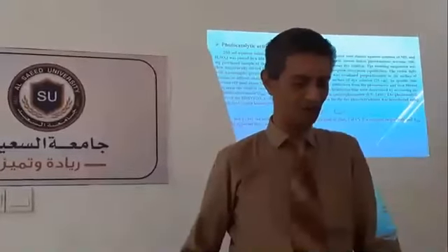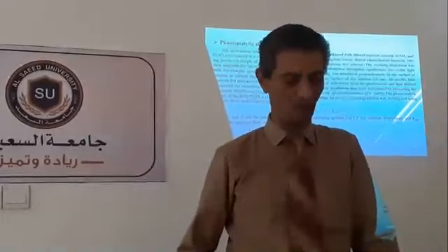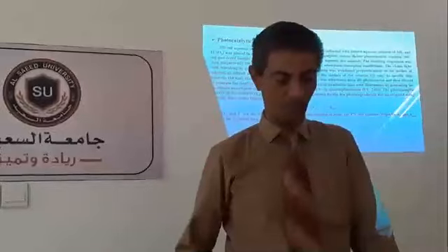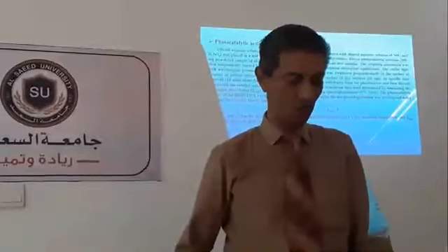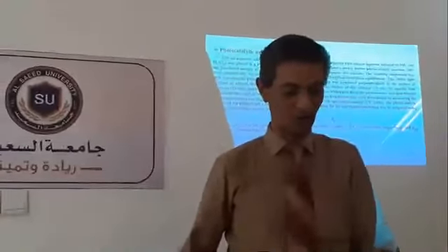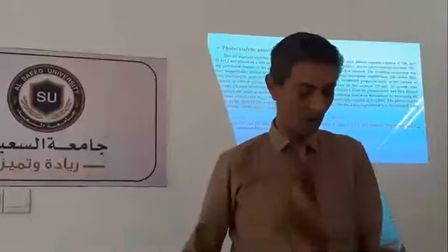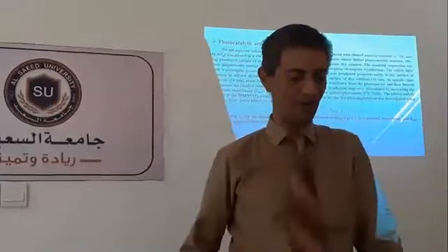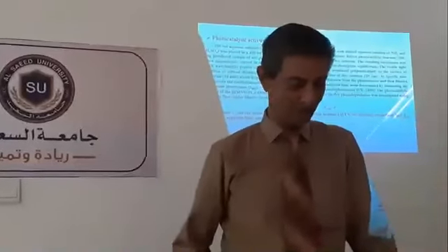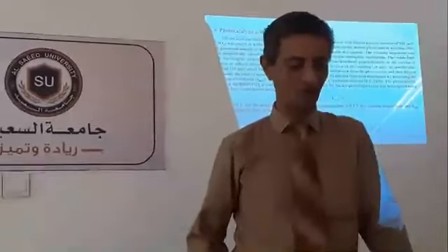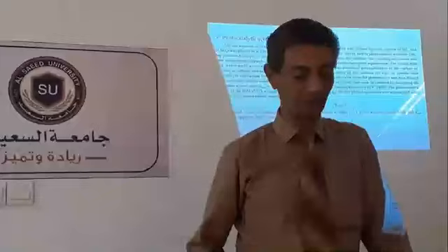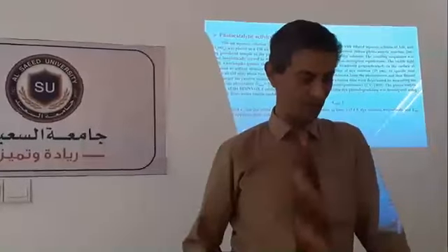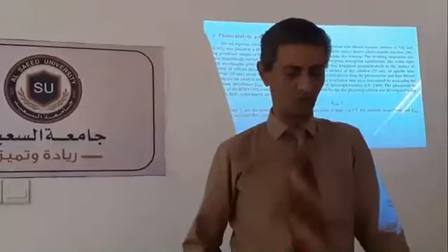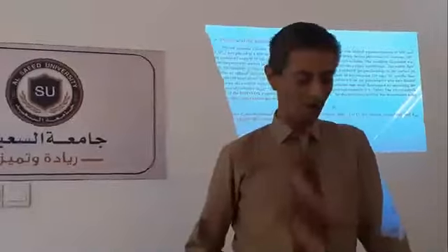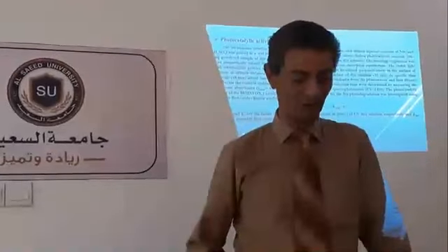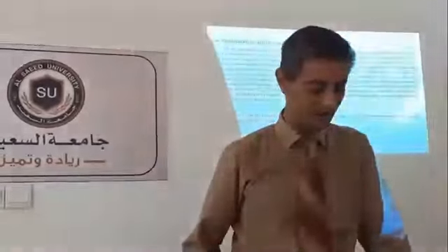Visible light with wavelengths greater than 400 nanometers, using a 300 watt xenon lamp, was irradiated perpendicularly to the surface of the solution, at a fixed distance of 25 centimeters between the light source and the surface of the solution. At a specific time of 10 minutes, about 5 ml of the reaction mixture was withdrawn and filtered to separate the catalyst. Concentration of dye at various irradiation times was recorded and measured using the maximum absorption on a Shimadzu UV-visible spectrophotometer. The photocatalytic activity of the catalyst for dye degradation was investigated using a pseudo-first order kinetic model.